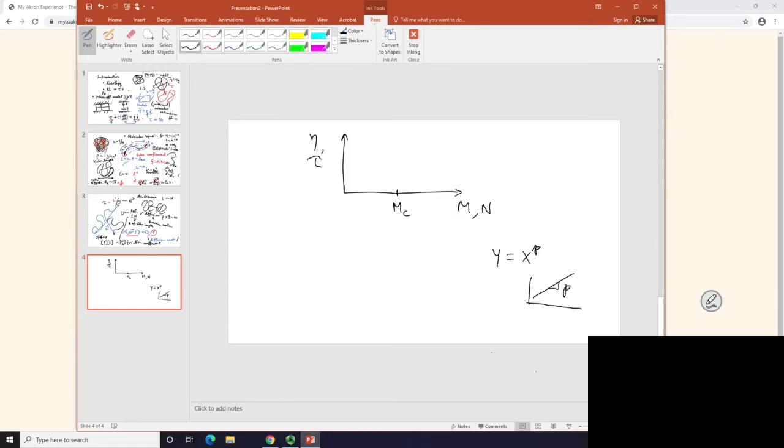Okay. So it turns out that the viscosity and relaxation time initially all change with molecular weight linearly. Slope is 1. And then, as Alex mentioned, it turns into 3.4 very strongly, beyond some critical molecular weight, Mc. When the molecular weight is sufficiently high, it turns to 3.4. And the theoretical calculation of 3 would be this red line.